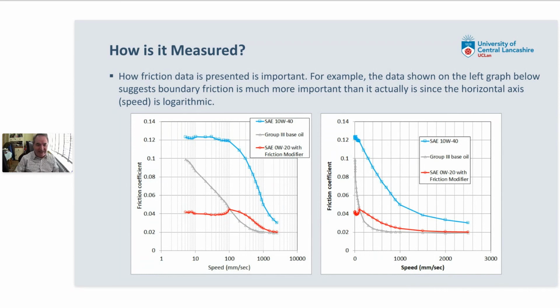If we plot the same data on a linear graph, we actually see that this boundary friction bit is a much smaller proportion of the test than it would seem if you plot it on a logarithmic scale. And for most machines, the proportion of time that you're in the boundary lubrication regime will be less than 1% typically, and you're more likely to be in the mixed regime than the boundary regime. So as tribologists, we do need to consider how results are presented and what perception those results give you by looking at the different ways they're presented. Although it's useful to plot on a logarithmic scale because you can get the wide speed range on that scale, it does sometimes give you the impression boundary friction is much more important than it actually is.